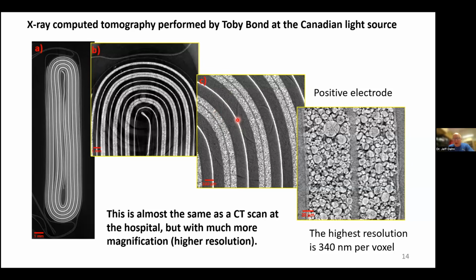This very bright line is the copper current collector of the negative electrode. And this dark material on either side is the graphite layer for the negative electrode. Then you can see the little spherical balls of the positive electrode next. And this gray line down the middle is the aluminum current collector of the positive electrode. The other side is also coated with positive, and then this whole structure repeats.